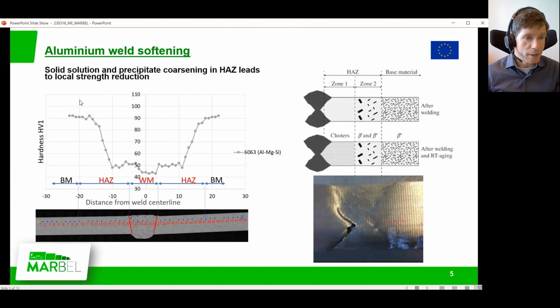And it is full strength away in the BM, the so-called BM, which is the base material, but then rapidly drops when it comes closer to the weld. And this is an area that is almost 20 millimeters away from the central line of the weld. So it's a rather large area, but still small enough to be very sensitive for straining. And this is also shown here, that it is approximately 50% of the hardness, which then represents 50% of the strength.